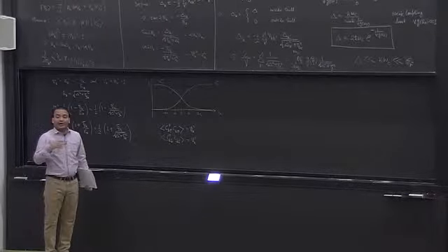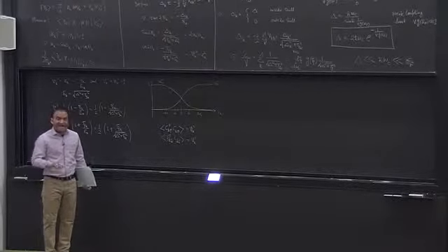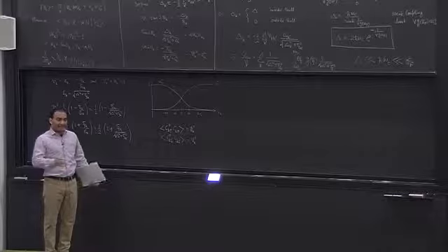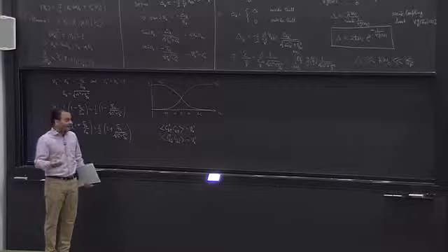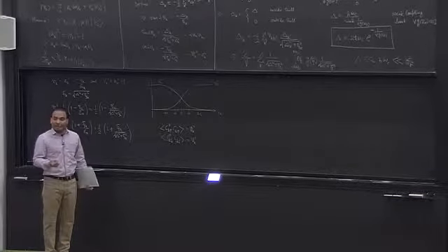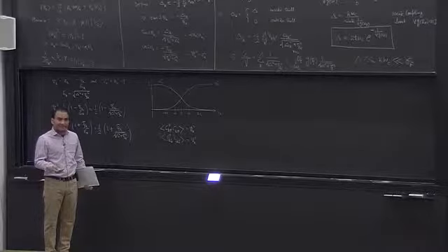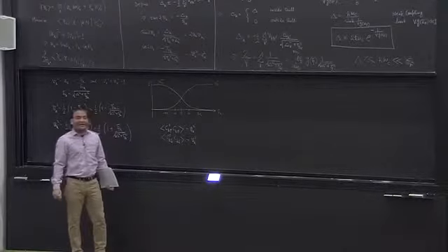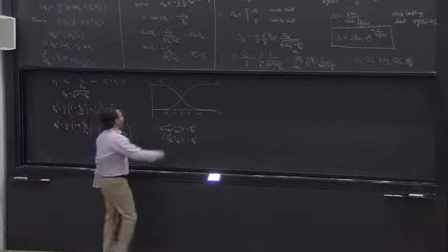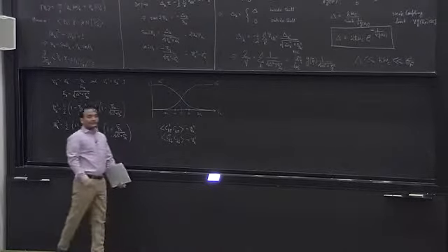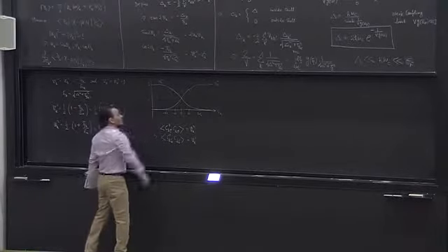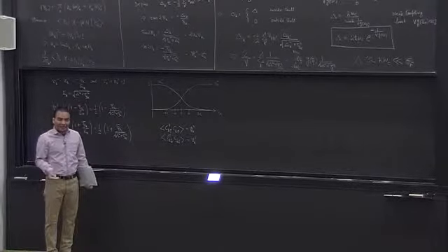If we plot the Fermi function at a finite temperature, the critical temperature Tc of the superconductor, we can figure out Tc experimentally, and knowing the dispersion, we can make a plot of the Fermi function at Tc as a function of energy. What we find is that this Fermi function is similar to Vk square. So the 0 temperature Vk square is similar to the Fermi function at Tc.